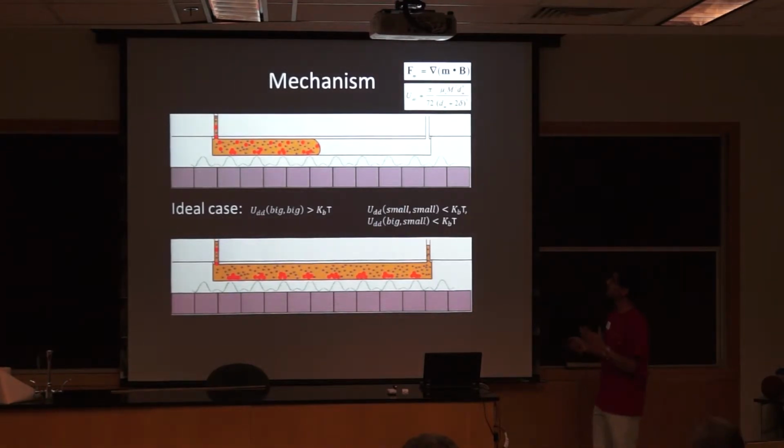So the mechanism here in another schematic is that these 20 and 5 nanometer mixtures come together, and wherever the gradient is high, since the magnetic force depends on the gradient that I showed you earlier, these larger particles start to settle down and cluster because of the dipole-dipole energy term being bigger than the thermal motion, and we can see these regions where they start clustering, whereas we don't want these smaller and larger particles interacting. So the small particles are just flowing through, and we get this out here, and all the bigger particles will be trapped in that channel.